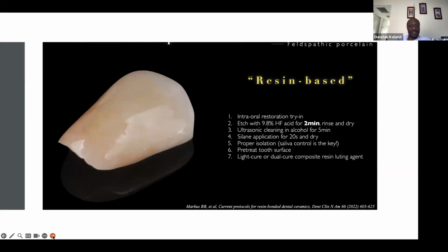If you're doing veneers, they'll be treated with hydrofluoric acid. That's the preparation of the bonding surface, or what they call the intaglio surface of the restoration. Then they'll do silane application, and then you can light cure or cure with any resin cement of your choice.